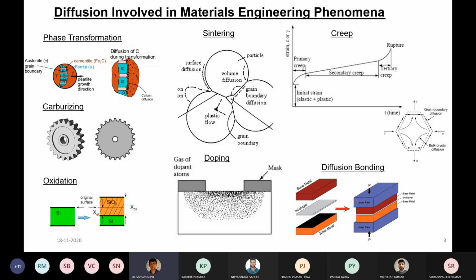So one should ask why one should reach the austenitic temperature, why high temperature is required, like 850 to 980 degrees centigrade, where the austenite phase is stable. Why are you looking at that? Because austenite, although it is an FCC crystal structure, has higher carbon solubility than ferrite, which is the low temperature stable phase for steel. Ferrite has less capability with respect to solubility of carbon. But if you check the atomic packing fraction of BCC iron and FCC iron, you will see that FCC iron is more close packed. Still, it can accommodate a higher percentage of carbon than BCC.